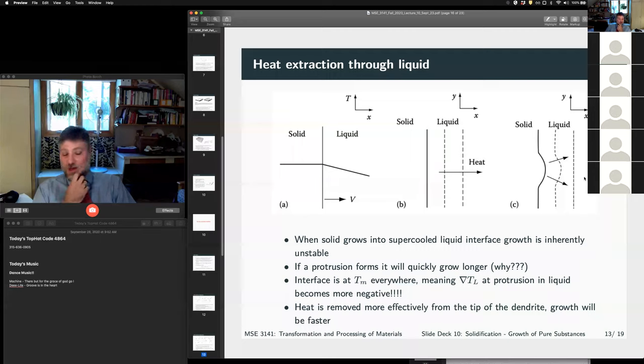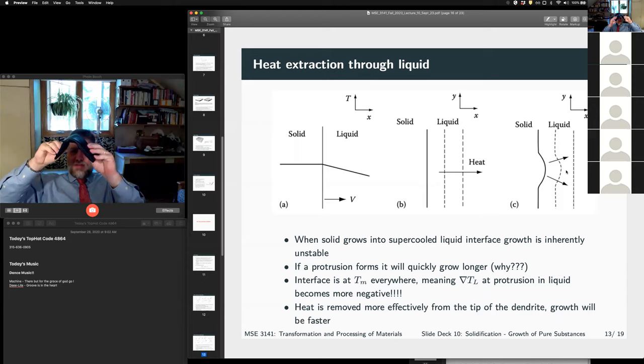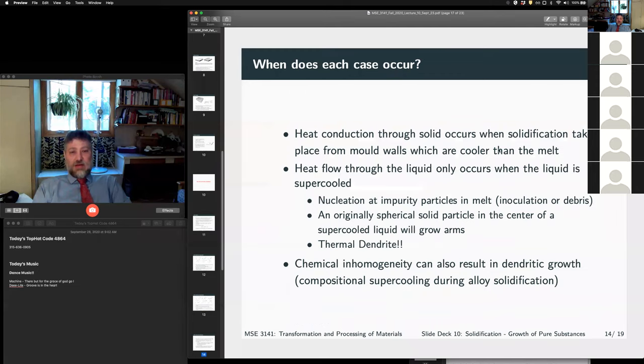We're conducting heat this way. So the velocity of this bump, the growth velocity here, is now going to be faster than here. So this protrusion will rapidly grow into the supercooled liquid, leaving behind this interface. So when we have heat conduction into the cooling liquid, we're going to have an unstable interface, and this protrusion is going to grow out, so we'll start flat and the growth will occur something like that. We'll get this bulge that then grows into the liquid at an accelerated rate. Okay,